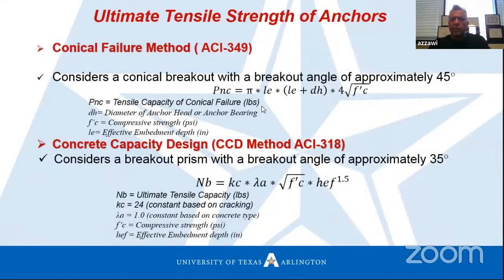The ACI code 349 gives us a formula to calculate the ultimate tensile strength of anchors, but this is without fibers. This is for normal concrete. Also, the ACI code 318-19 in chapter 17 gives us another formula. It is modified and gives us more accurate results than the other one. They consider a concrete breakout prism with an angle of approximately 35 degrees. This formula could be used for plain concrete to find the ultimate tensile strength of anchors. But as we see, it is without fiber.